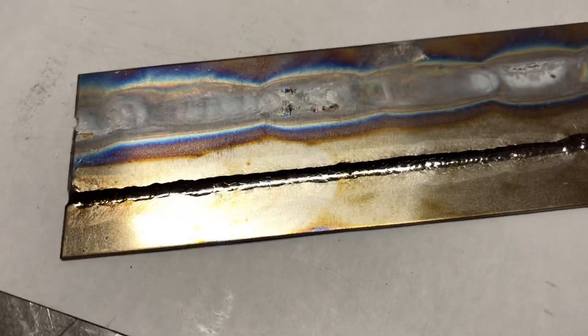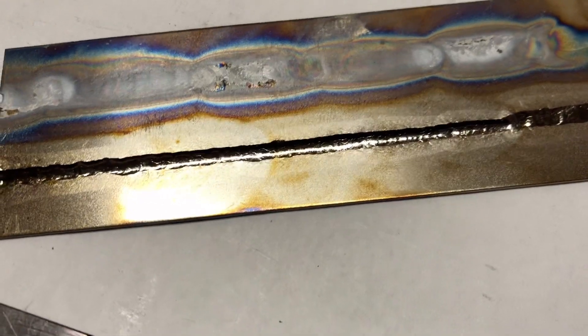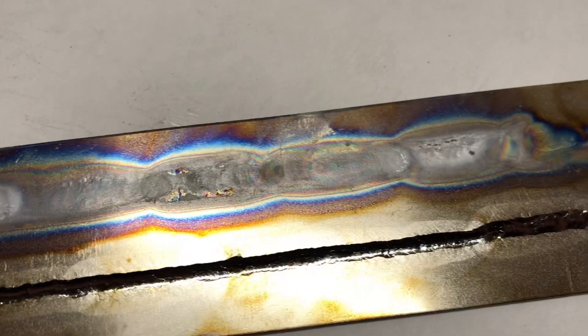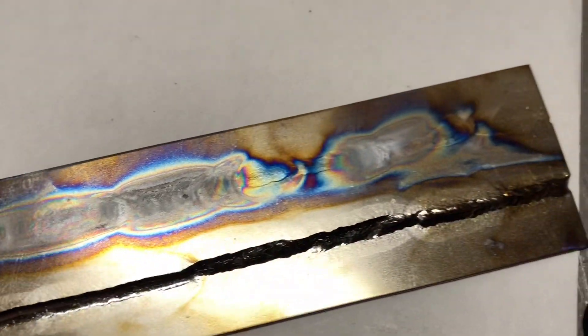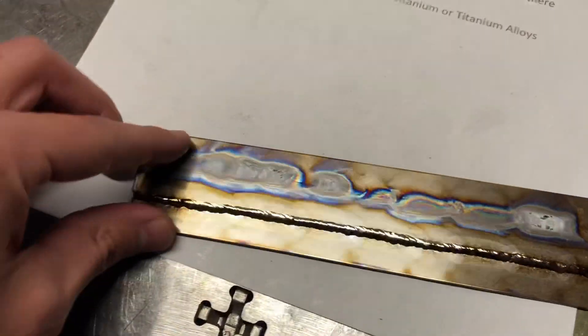You want to see these silver colors or some of this brown straw color. You can see on the backside here, this is a gray dull color. That is a color you do not want. That is bad — this is just the backside of this piece.